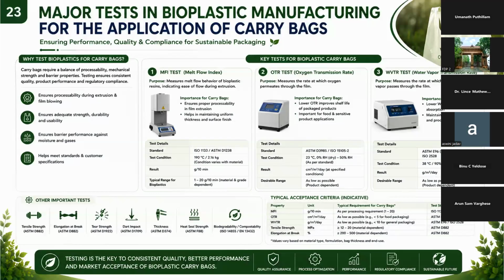The expected result for a thin film carry bag should be less than 10 cubic centimeter per square meter per day. The next test is the water vapor transmission test. This OTR and WTR value determines the shelf life of our carry bags. The main principle of the OTR test is that we keep our film in a chamber, and oxygen travels from a high concentration zone to a low concentration zone. That transmission value is taken as the final value.